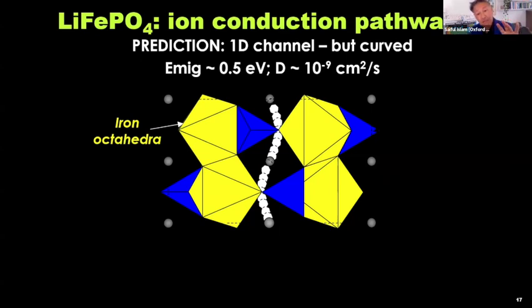The yellows are the iron octahedra, the blues are the phosphate, and the greys are the lithium ions. So in terms of atomic scale insights, we can actually look at how lithium ions move in this lithium iron phosphate. We predicted that it was a 1D conductor, but that 1D conductor wasn't a linear path, but a curved pathway with an activation energy of about 0.5 eV, and again, a diffusion coefficient of 10 to the minus 9. What was interesting, this was a clear prediction from modeling.